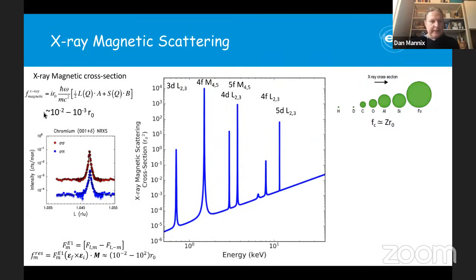If you actually look at the cross-sections here, what you can see is that there's a solid line background. This is what's called a non-resonant scattering term, which is really going as the square of energy. And then you come to these absorption edges where you can just tune into them and you get this great enhancement of magnetic scattering. And that is the effect that we really want to tune into. So this is where we can boost our magnetism and study very thin magnetic structures that I've just shown, or even look at magnons.